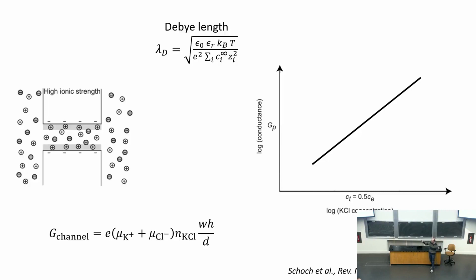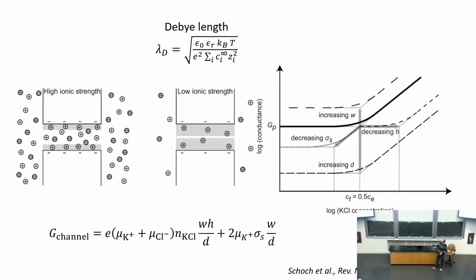So the more concentrated your electrolyte, the shorter the screening will be, and you'll get this channel conductance here, which is pretty much the bulk conductivity times the cross-section of your channel divided by the length. Now, if you decrease this concentration, you'll see that the Debye length becomes longer. Longer Debye length means at some point you'll have overlap. And so in your channel, you'll only have counter ions accumulating. And so in this case, you'll start to have surface-governed transport. Surface-governed transport corrects this equation by this term here. And so in experiments, what you should see is a deviation from your bulk behavior into a surface-governed behavior here.